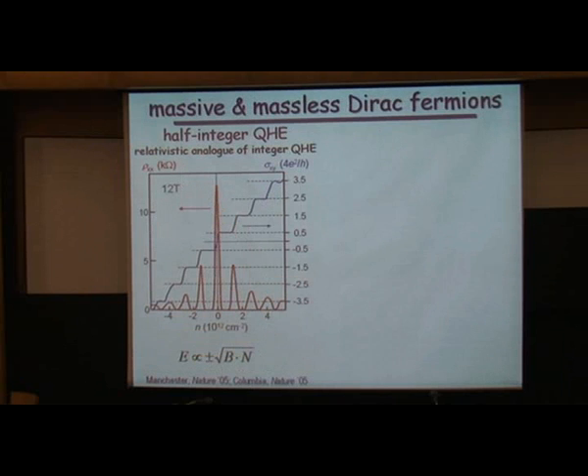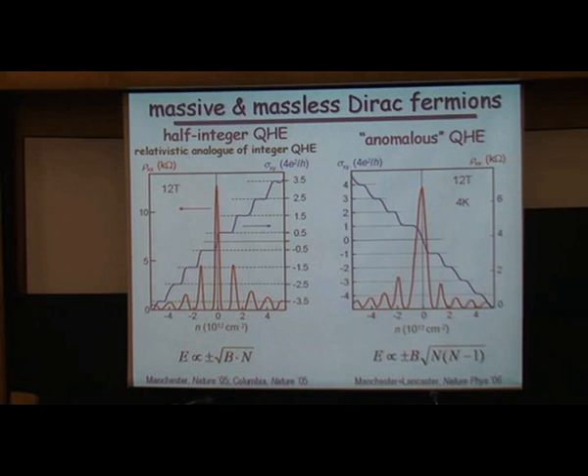In addition, when we put it in a quantizing magnetic field, we see something unusual. Not only is the electronic spectrum linear, but there is also the so-called quantum Hall effect, which is not trivial but shifted by a factor of a half. Usually for a parabolic spectrum, you expect plateaus at integers. We see them at half integers, and combined with cyclotron studies, we know that the quantized energy is not the normal energy for electrons. In addition, there is such a system as bilayer graphene, and in this bilayer graphene the quantization is also different, and the quantum Hall effect is different. We know from the combination of those measurements that quasi-particles in these two materials, graphene and its bilayer, are described by Hamiltonians which are not the normal Schrödinger Hamiltonian, but those two.